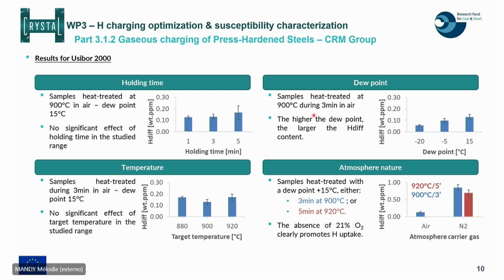On the right side, we will see a more important impact. It's more about the atmosphere parameters. You see first the dew point, which is represented here. You see that the higher the dew point, so the wetter the atmosphere, the higher also the diffusible hydrogen that is absorbed during the austenitization process.